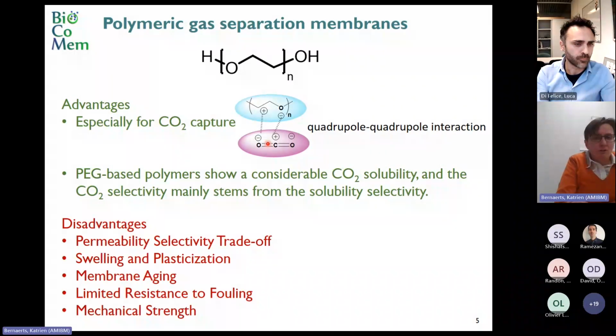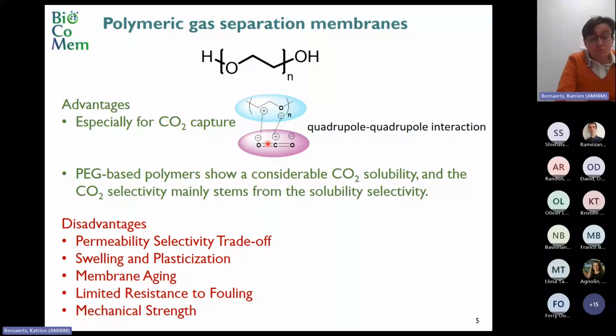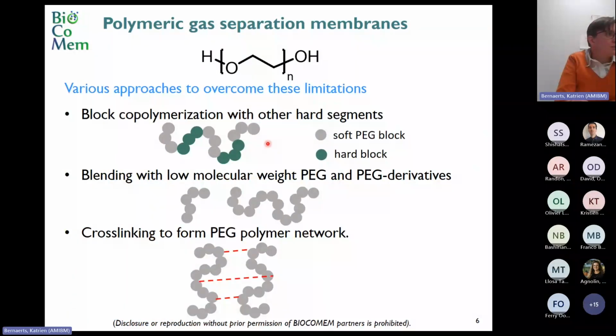The disadvantages of pure polyethylene glycol-based membranes are that there is a trade-off between permeability and selectivity. Often you have swelling and plasticization, which gives you deterioration of the properties. Also, the polyethylene glycol suffers from aging, and thus also the membrane. There is also limited resistance to fouling, and the mechanical strength is not what it should be because polyethylene oxide is a soft polymer. So various approaches exist to overcome these limitations.